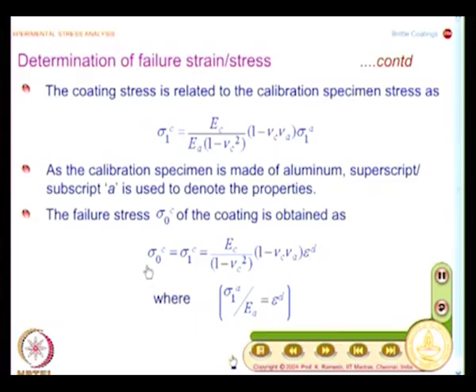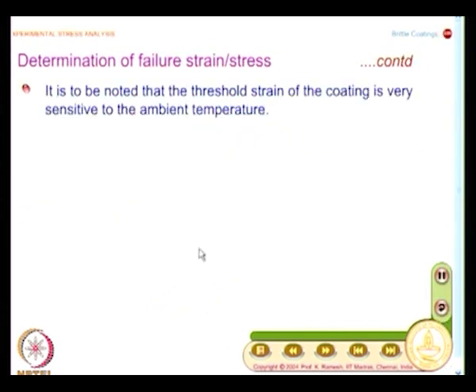So, you should not take the incremental loading casually. You have to estimate fairly accurately what would be the desirable increment for a particular component on hand to find out the failure strain, and you roughly know it will fail around 300 to 350 microstrain. So, you can do your experiment very carefully and not miss this. That is what is important. My interest is to show how the Poisson ratio mismatch can affect the result. So, I will also find out the corresponding specimen stress. When the coating fails, there must be some specimen stress for which the coating has failed, and I can bring in the Poisson ratio of the specimen and look at how this affects it.